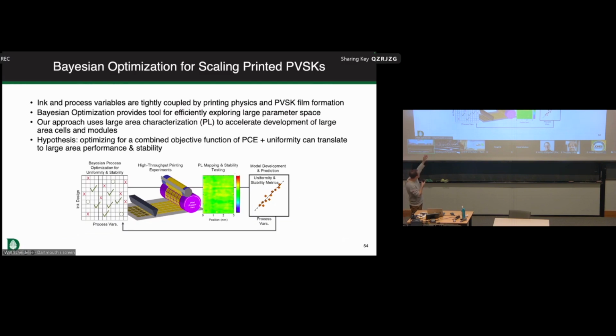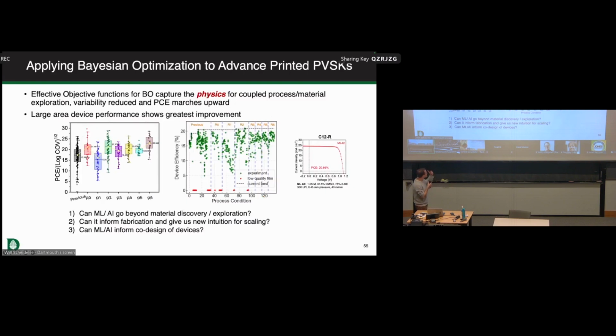So it's a sequential learning method that uses Bayesian optimization to take all of this information we have now, right? We have the correlation, or we have the data and its dependencies on the printing physics. We have the dependencies on the ink chemistry and everything else, the mechanics of the contact pressure. And the Bayesian optimization gives us something that you really can't wrap your head around as an experimentalist. As an experimentalist, we're really good at mapping things out along single variables. But it turns out if you want to explore a 7-dimensional space, that's a really inefficient way of doing it. So Bayesian optimization, on the other hand, can allow us to sample that space, create this Bayesian process model, and then march forward and improve the efficiency of the solar cell in this case.